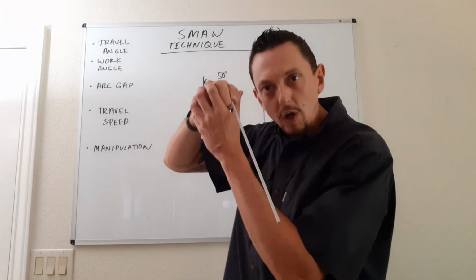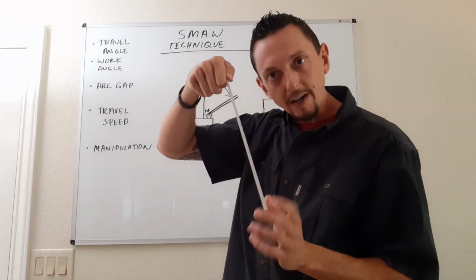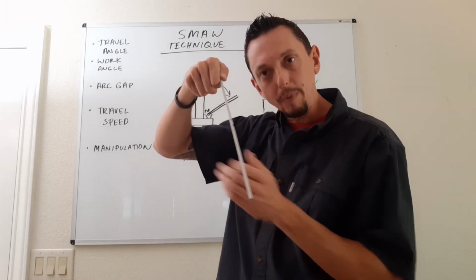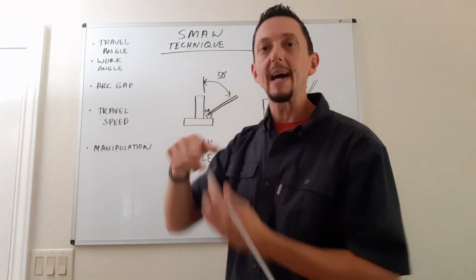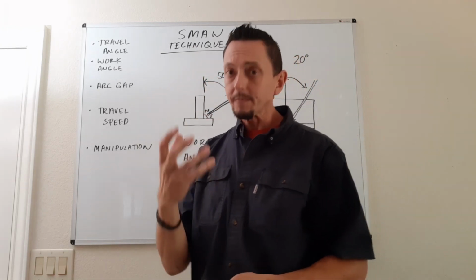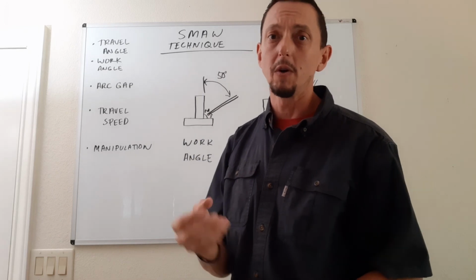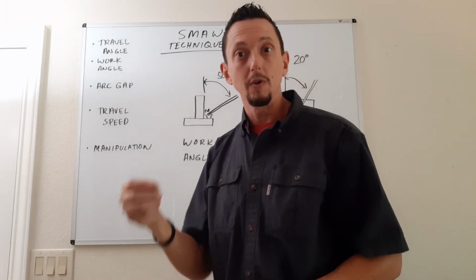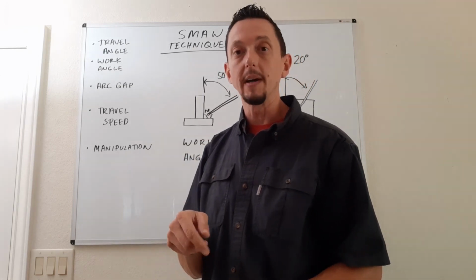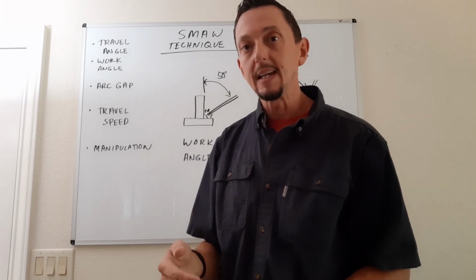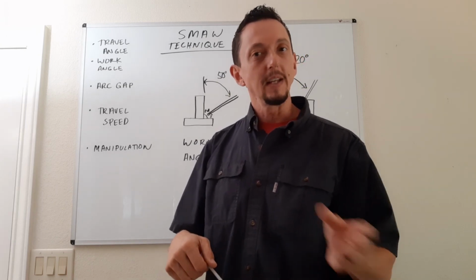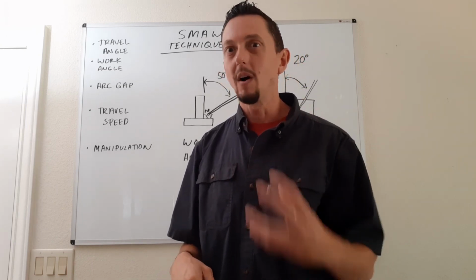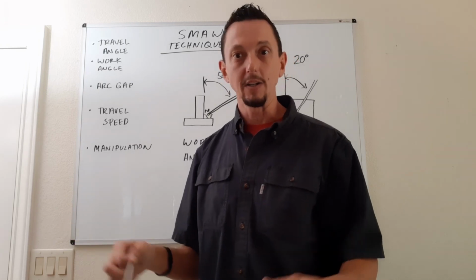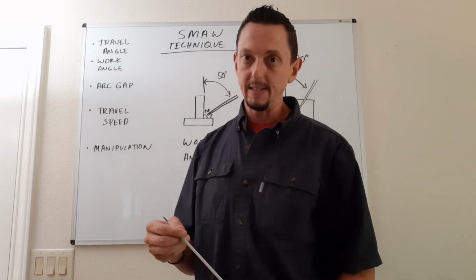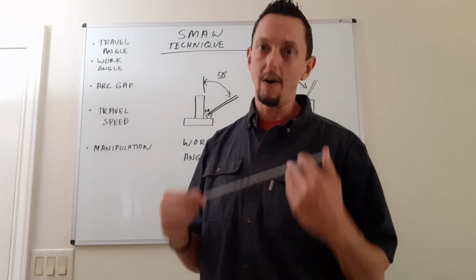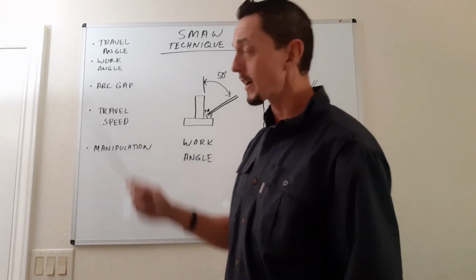So always be trying to watch the arc spacing as that electrode burns away and keep it nice and tight. That's going to give you the most control, it's going to give you the most control in terms of where your weld metal is actually going, but it's also going to control the heat in the weld pool. Get that long arc, it's going to start to get real hot and erratic, and it's going to feel out of control, okay? So try to maintain tight arc spacing or an arc gap.